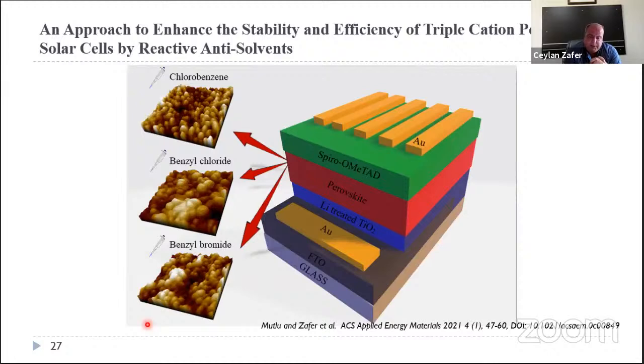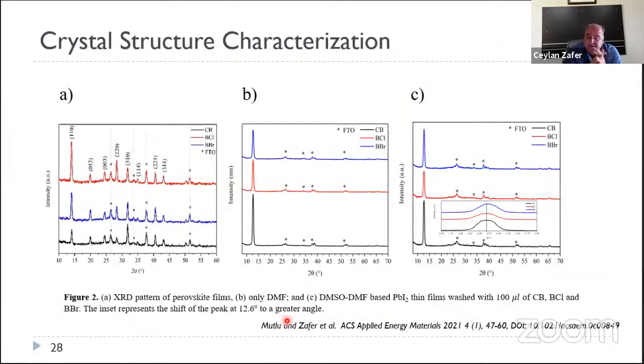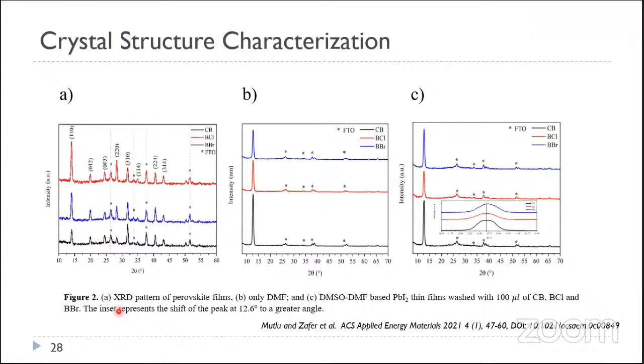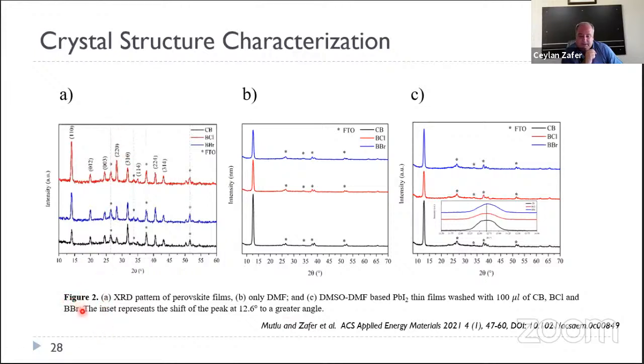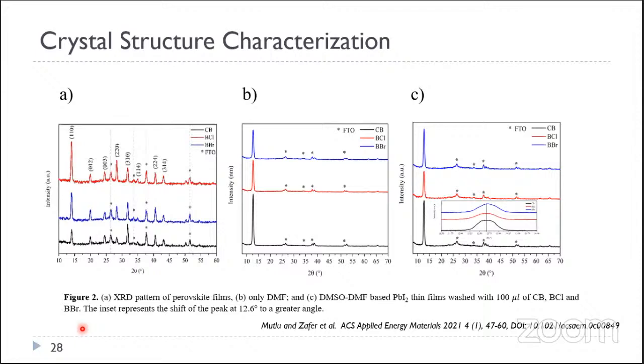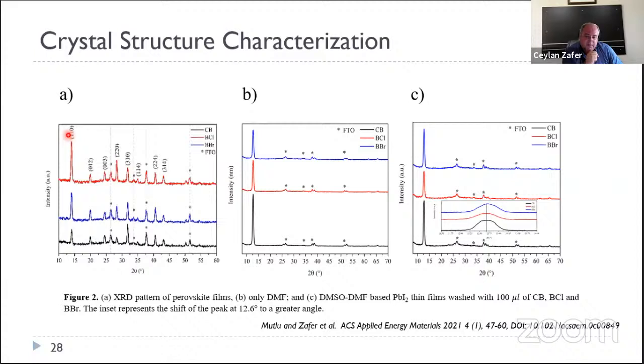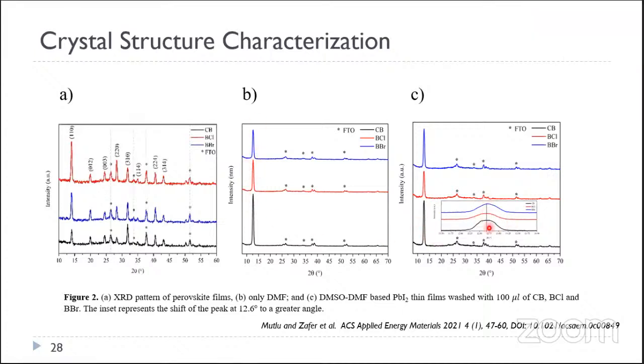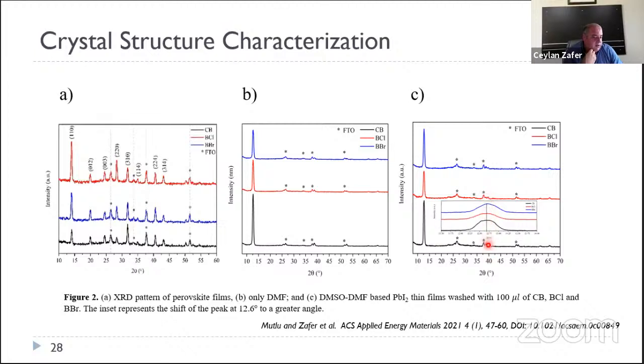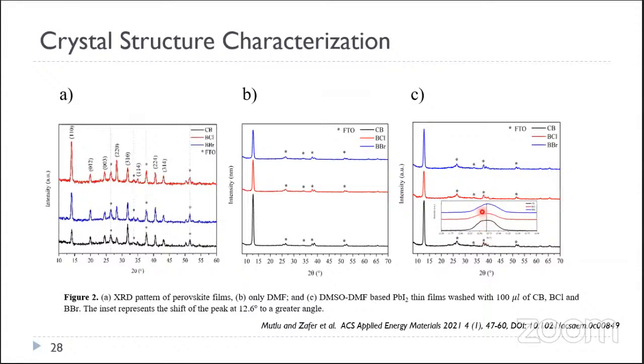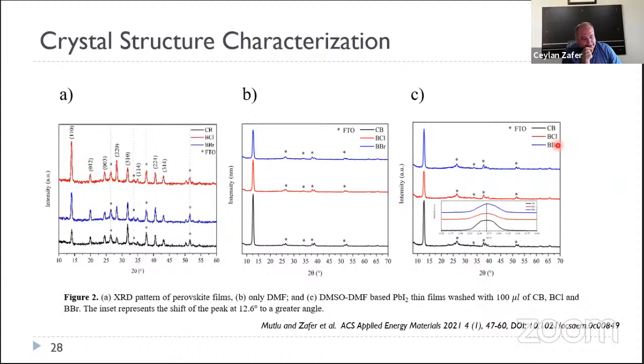With the first one, we used benzyl chloride and benzyl bromide instead of chlorobenzene, and with this changing of the solvents, we observed some differences within the perovskite crystal structure examined with the X-ray diffraction studies. This peak located at 12.6 is a common peak of the perovskite material coming from the lead iodide. The peak intensity will show you the crystallinity, and you see a small shift here at 12.6 2-theta degrees. This is evidence of the insertion of the larger ionic radius halogen into the perovskite structure.